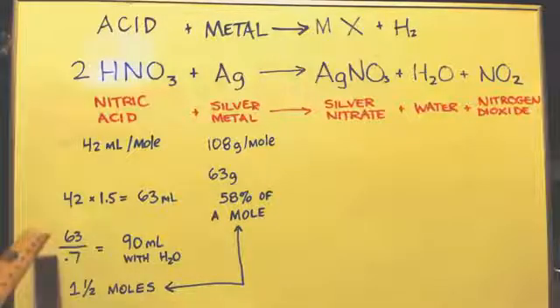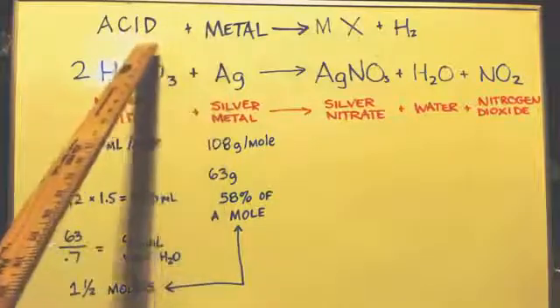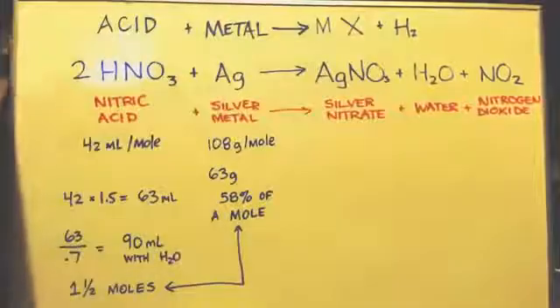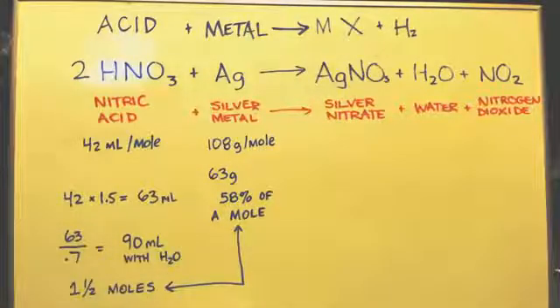Here's my stoichiometry. I want you to realize that when you put a metal in acid, normally you get the metal salt of that acid plus hydrogen. Okay, meaning if this is hydrochloric acid and this is iron, you get iron chloride and some hydrogen. If it was zinc, you get zinc chloride and some hydrogen. But when you put metal in nitric acid, it's a little bit different. When you put this into there, you still get your metal salt of the acid, right? Because you got nitric acid, so you get the metal nitrate. But instead of evolving the hydrogen, you're evolving NO2. And actually a little bit of NO also, but it'll easily oxidize to this just from the oxygen in the air and water.